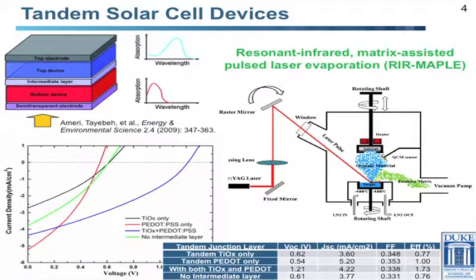So in my group, we've just started looking at some of these devices and basically trying out different types of intermediate layers. And I'll just tell you a little bit about how this MAPLE works and what's different about it. So it's basically a variation of pulsed laser deposition with two big differences. One is that it uses an infrared laser, so you don't damage these organic or plastic materials that you're trying to deposit. And the other big difference is that the target is actually a frozen emulsion as opposed to a solid polymer target.